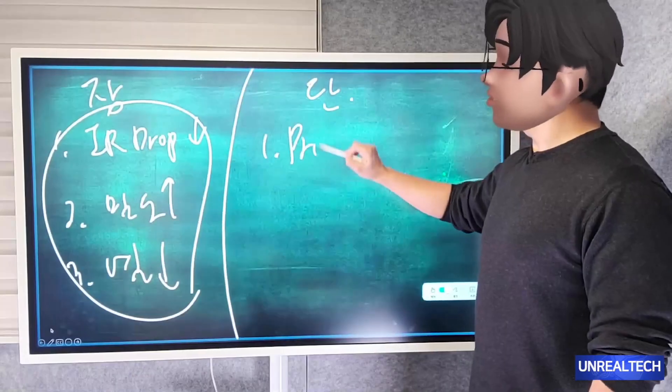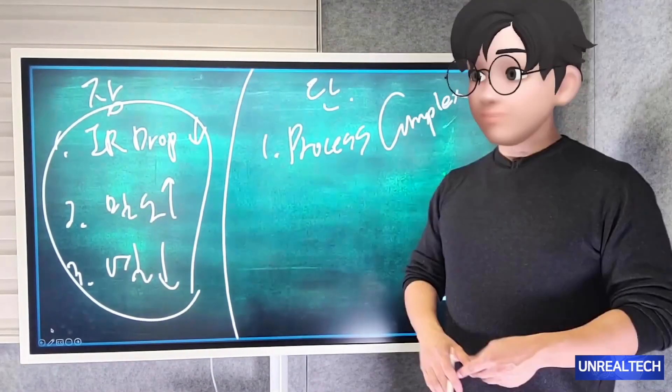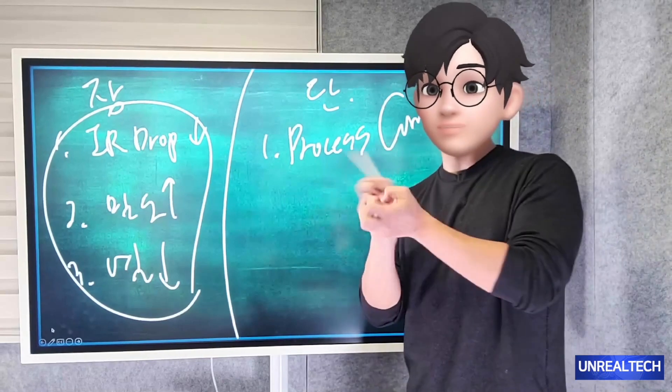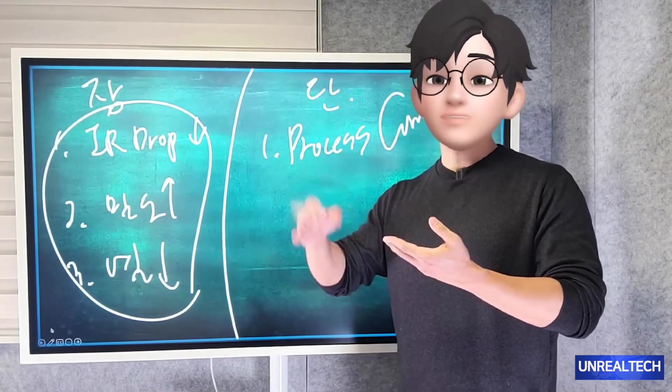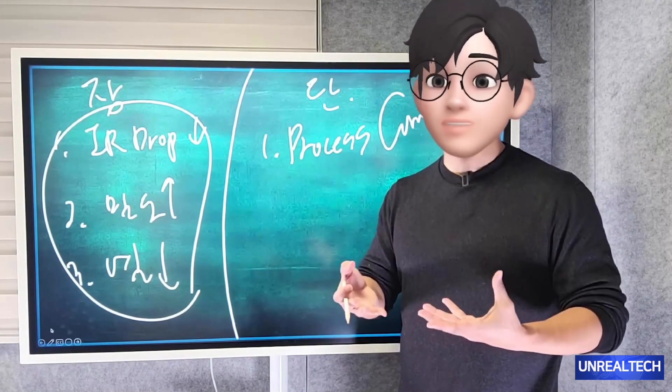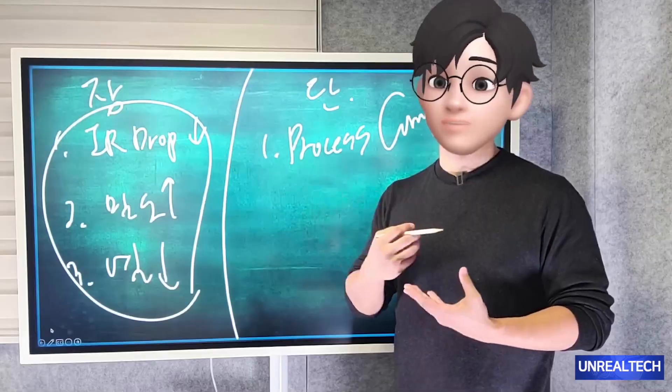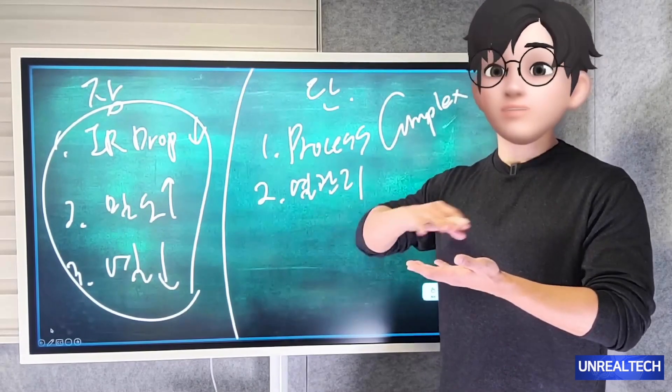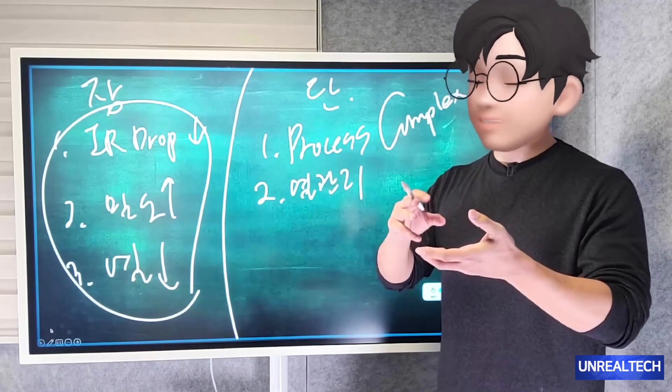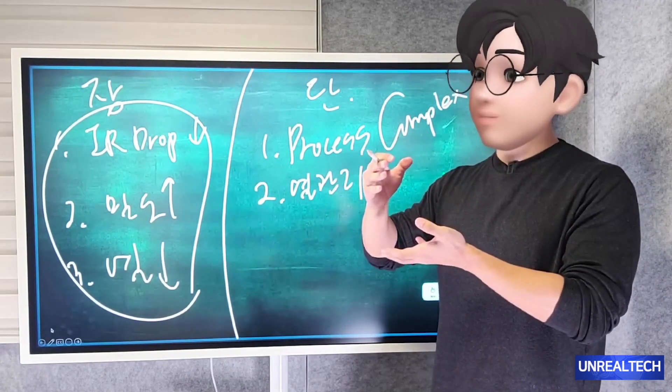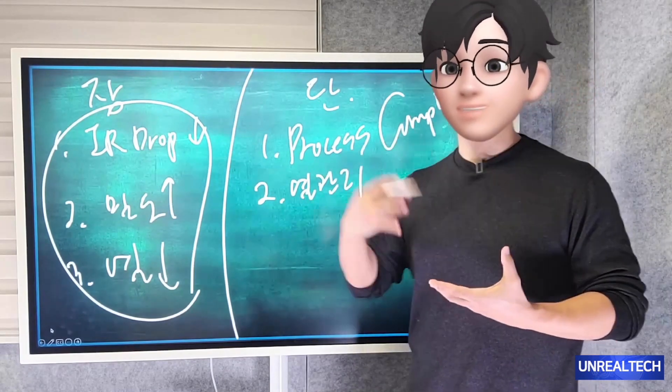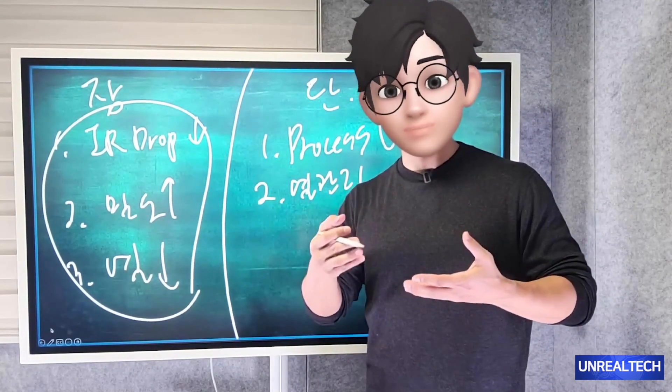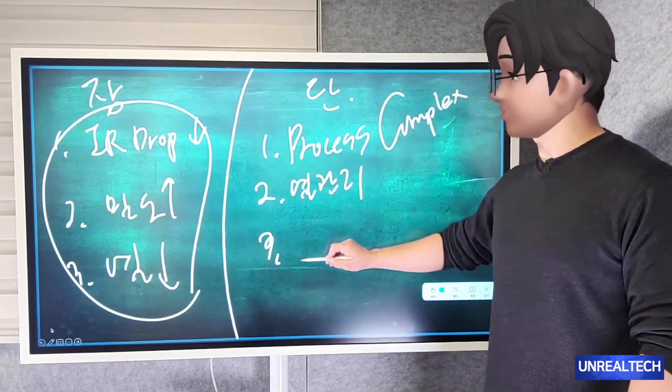So what are the drawbacks? The process is inherently very intricate. We need to not only work on the front side of the wafer but also the backside. This involves grinding down the backside, creating TSVs, and depositing metals. Essentially, these are additional steps that were not part of the original fabrication process. As a result, additional processing steps are required, which inevitably increases costs, and new equipment needs to be introduced. Secondly, while heat dissipation is good, managing it might be difficult. Historically, all the components were fabricated solely on the wafer's front side, which guided our density and layout calculations. However, with the new approach of utilizing both the top and bottom, we must re-evaluate the thermal dynamics in this novel setup. If the backside is merely coated with metal layers, it could pose significant challenges for heat dissipation. Thirdly, and most significantly, the yield remains uncertain. Essentially, it's about thinning the wafer. When the process of thinning the wafer is not executed accurately, it becomes highly susceptible to breaking. Moreover, drilling TSV holes can cause the wafer to crack, making yield management for this new process quite difficult.